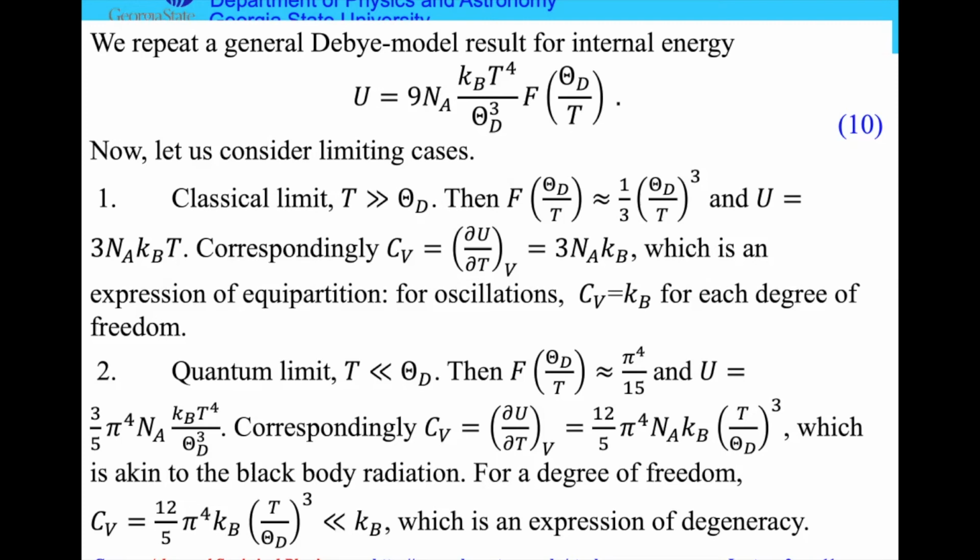It's understandable. At low temperature, only very low frequency phonons are excited. They do not reach the boundary of the Brillouin zone, so the dispersion relation is perfectly linear. And how the curve ends, what is the second assumption of Debye, does not matter, because phonons never reach the end of the zone, never reach the limiting frequency. Therefore, the expression works so well.